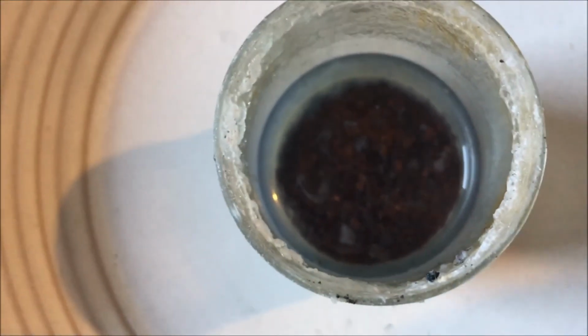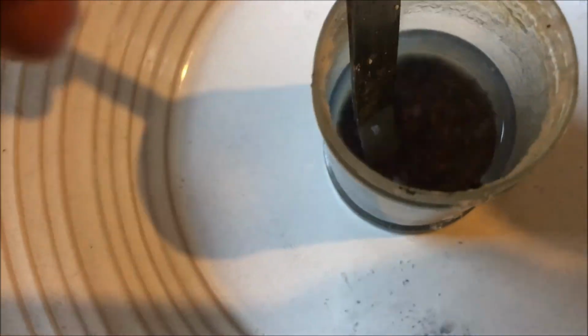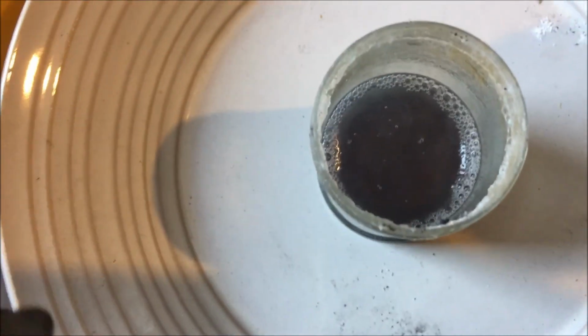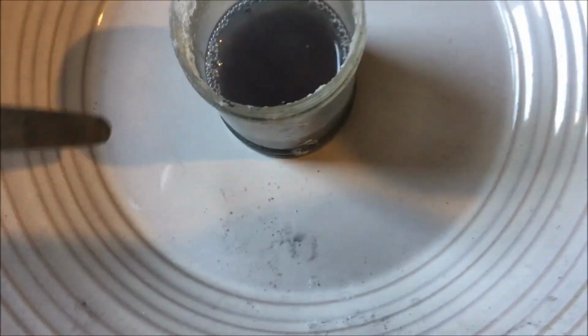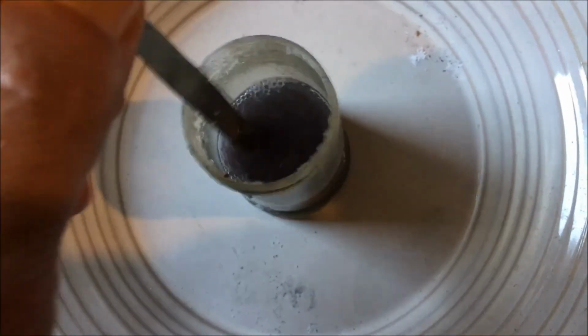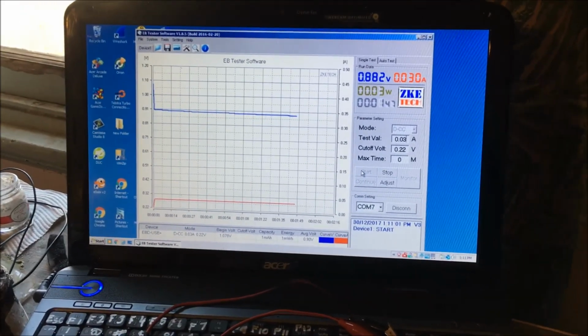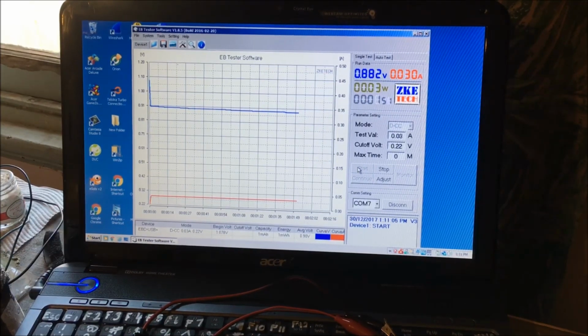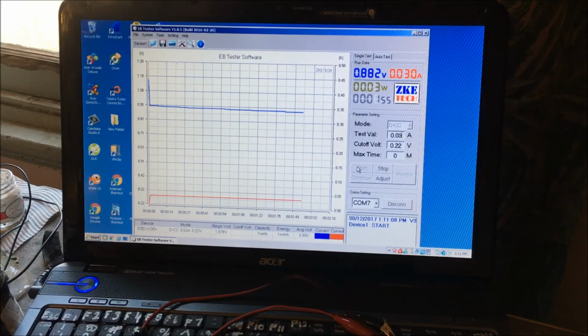The particle size looks around about the same size, but you watch the amount of bubbles that come out of there. That just generates bubbles. So there must be some sort of energy locked up in there. But the liquid doesn't seem to be dissolving any more than it was. And so far that cell's holding up not too bad. We're still at the 0.8 and it's 2 minutes. So it's looking good for the zinc cell actually. The zinc carbon structured cell electrode. Alright, I'll get back when this discharges.